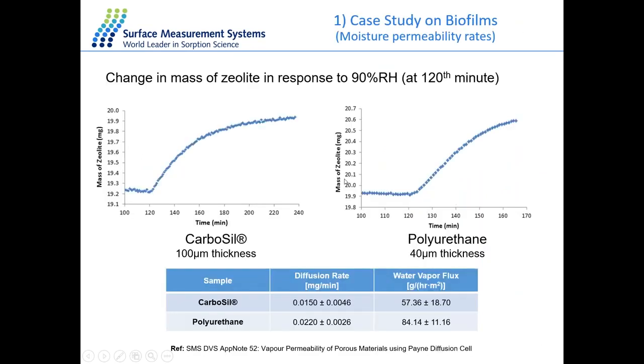And I have a case study here, which is related to polymer films with different thickness. So we have the CarboSil film, around 100 micrometers thick. And we also have a thinner film, the polyurethane film, around 40 micrometers thick. We use the Payne cell to measure both diffusion and permeability at 90% RH with zeolite inside the cup at 25 degrees.